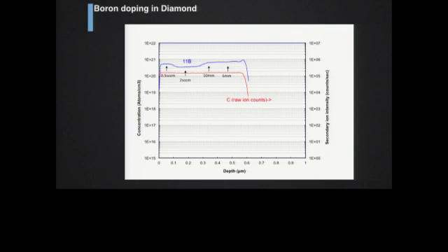So you see right here, this is the background. That's just the carbon signal. So we normally take that to make sure that there's no strange things going on with the SIMS data. So that should be uniform throughout the whole sample, and it is. And then what we've done is we turned on different pressures of gases of the methane during the growth process. And you can see how we can kind of vary the incorporation.